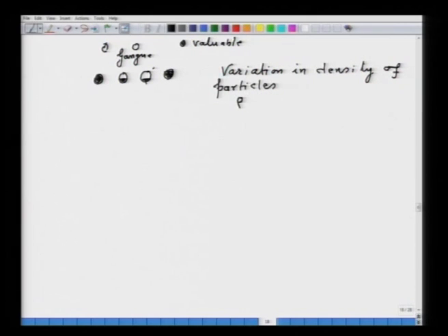It is clear that the density of a pure mineral particle is definitely greater than the density of gangue mineral. Now, in between these two, different particles with different proportion of mineral will have different density. So, that is a key point for developing the concentration technologies.